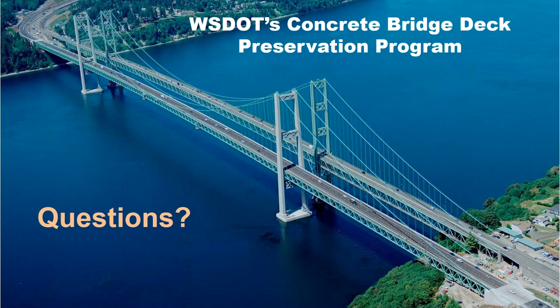Yes, there are several questions. The first question is, does WSDOT use any sealer for bridge deck preservation purposes? Yes, we do. We have a program with our maintenance forces where we're using some preservation money to do deck sealing on selected bridges. We're looking at some of the older concrete overlays that have cracks in them. We're going to seal those. We're also looking at some of the newer bridges to do some sealers, and the sealers come in two different versions. There's a silane, which is basically a water repellent, and then there's methyl methacrylate and epoxies that are actually a crack filler. As you drive around the state, you might start to see some of these sealers, where there'll be different colors on the decks, from time to time in different parts of the state.